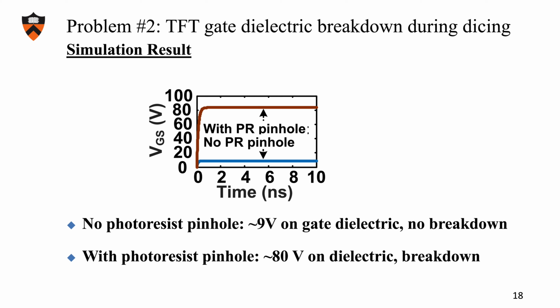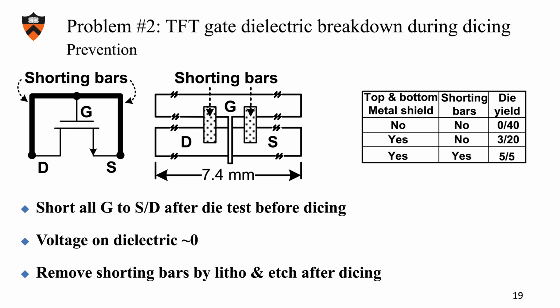Our approach in this work to prevent this damage is to use shorting bars to short all the gates to their source drains after die test and before dicing, so the voltage on the dielectric during dicing is kept almost 0 volts. The shorting bars are removed by lithography and etching after dicing. By doing this, from the comparison table, we can see that the dicing yield is increased from 0 out of 40, 3 out of 20, to 5 out of 5.